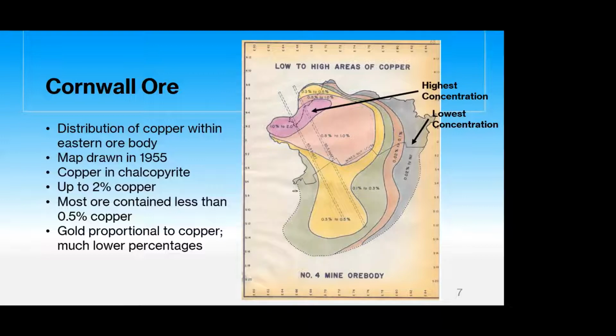So miners found the highest concentrations of copper in the ore up here near the top of the ore body, close to where the number 4 and the number 5 shafts penetrated through the soil down underground. Most of the ore body contained less than 0.5% of copper. Because the gold substituted for copper in the chalcopyrite, the concentration of gold varied proportionately to the concentration of copper in the ore, albeit at far lower percentages.